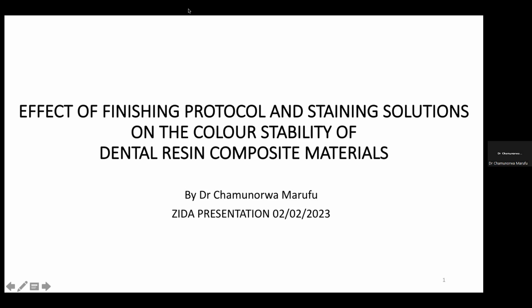All right. So for mylar strip, in as much as the mylar would exclude the oxygen from the restoration, preventing the formation of an oxygen-inhibited layer, which we know causes problems like this, some others have reported that the composite material underneath the mylar strip has a higher content of resin compared to composite material deeper within the restoration. So in as much as it gives you a very smooth finish, still that resin component actually plays an important role in discoloration of these composites.